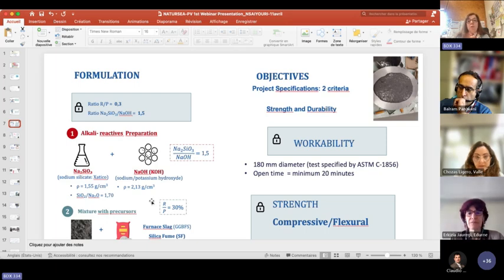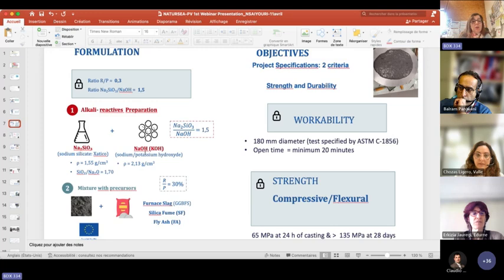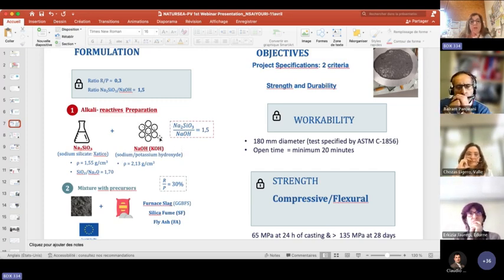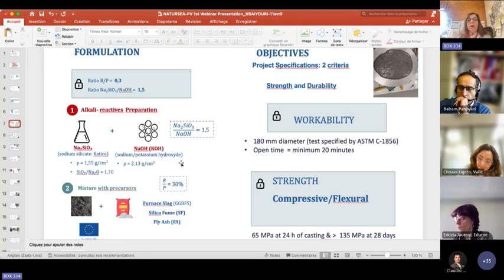In our work, we try to formulate with two parameters, and we will discuss these two parameters: alkali reactive preparation and also the mixture with precursors. For our case, we used sodium silicate and sodium or potassium hydroxide. We need to respect some ratios. I won't go into these details because it's something changing according to the whole formulation. We need also to use precursors like furnace slag, silica fume, and fly ash, which work with that reactive. And we need also to respect a ratio of reactive to precursor. This is the methodology, or the principle, of how we did our mixes.